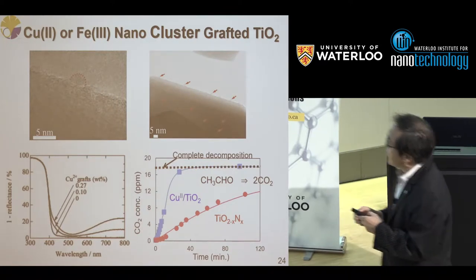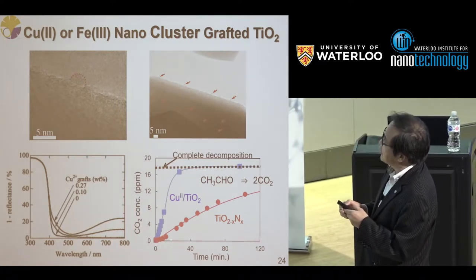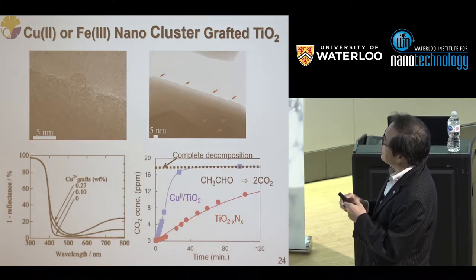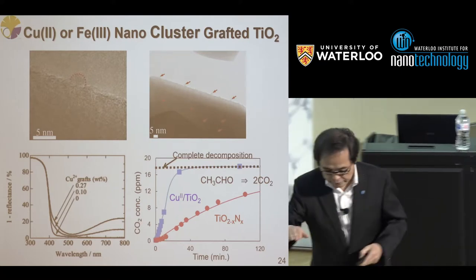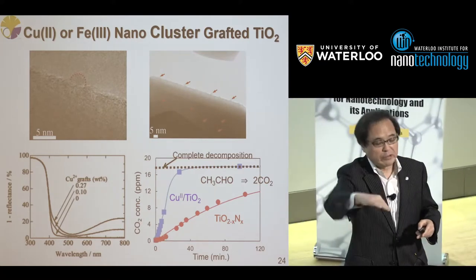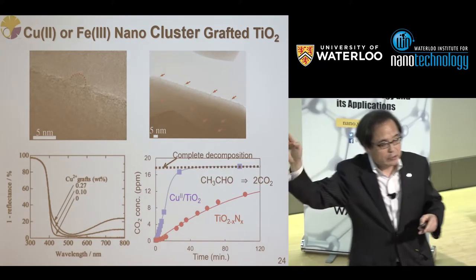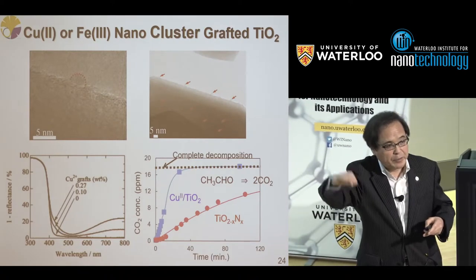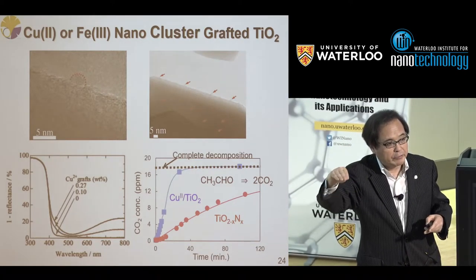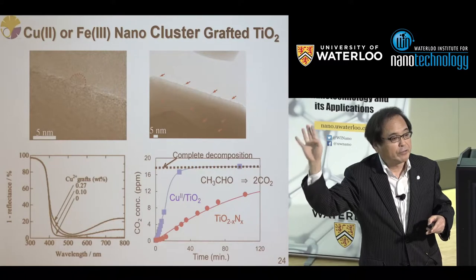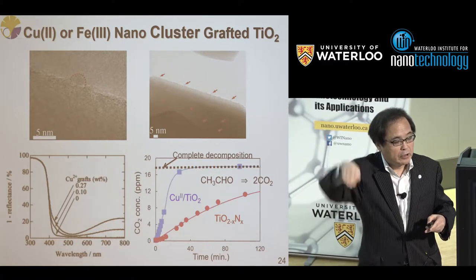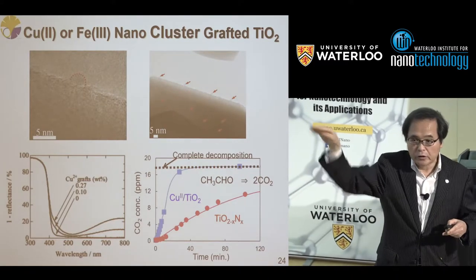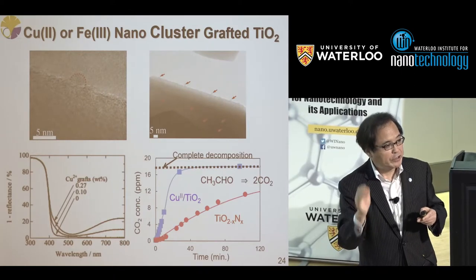And one of the most famous and most studied visible light sensitive photocatalysts is nitrogen doped titanium dioxide. This is the case of raised valence band. Okay, as I told, when we raise the valence band, oxidation power is decreased. That's why complete decomposition is rather difficult. But in our case, we can easily decompose. We did not sacrifice the oxidation power.